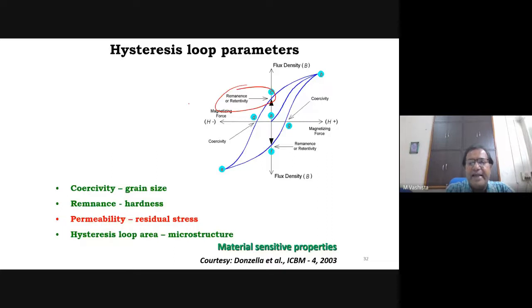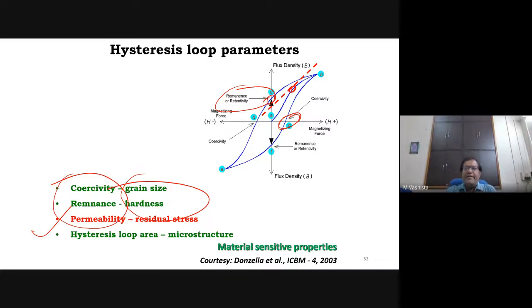Hysteresis loop characteristics like remanence or coercivity, and one more property the hysteresis loop has is permeability. Permeability is the slope of the tangent at this knee. These intersection points with the x-axis and y-axis will indicate remanence and coercivity, and the slope of the tangent at the knee of the hysteresis loop will indicate permeability. These properties, coercivity, remanence, and permeability, will give the mechanical property. So we can assess and characterize the material by using magnetic property easily, and this technique is safe also.